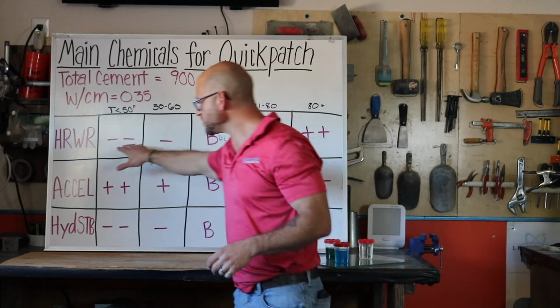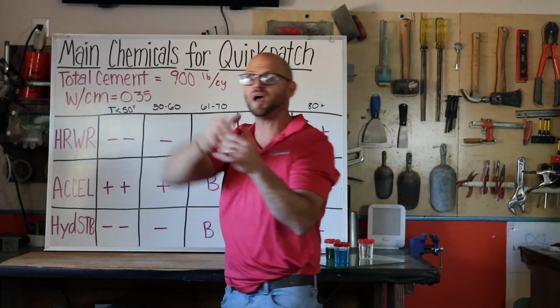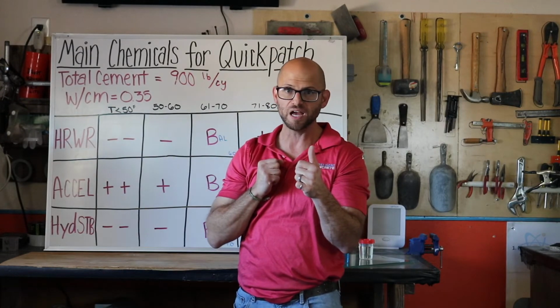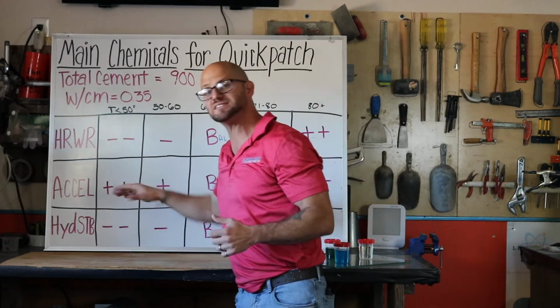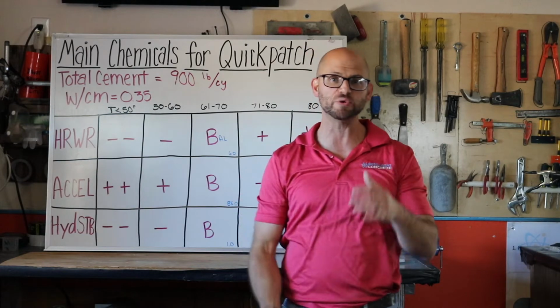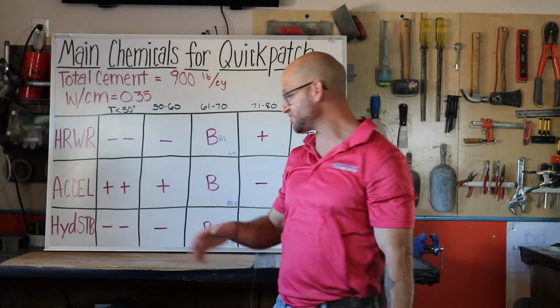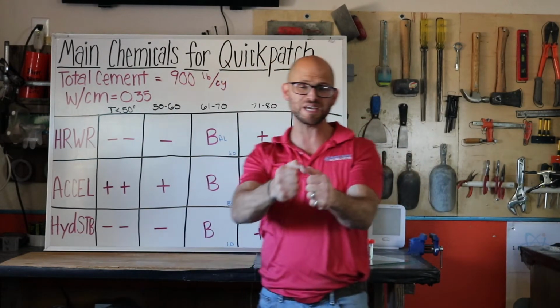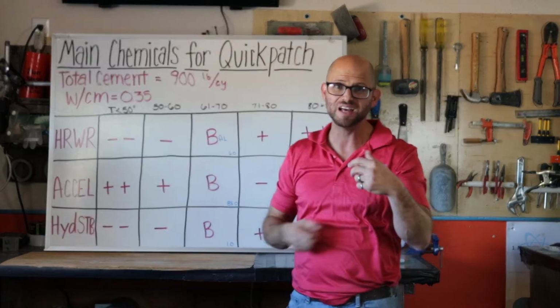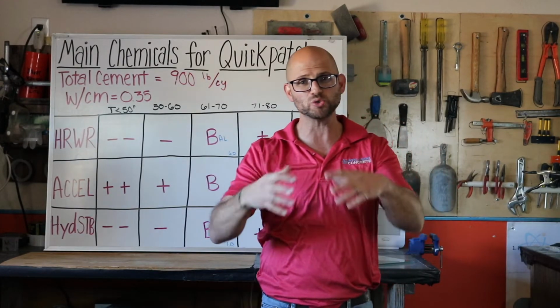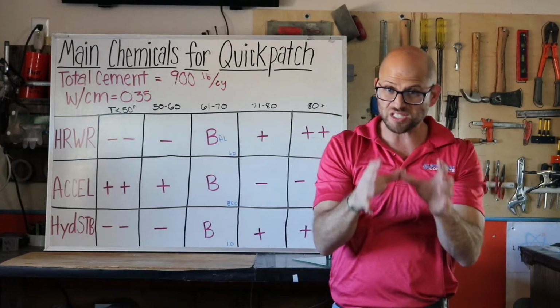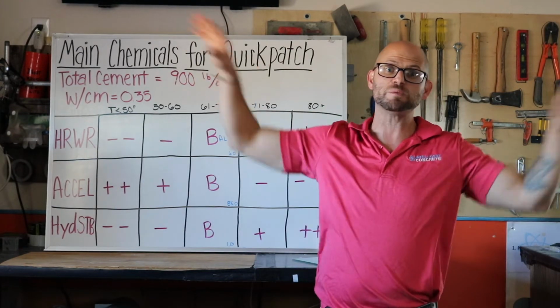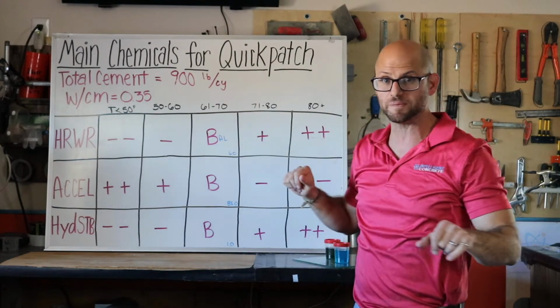Now, if I go 10 degrees colder than that, again, I might go half a step back on my high range water reducer, but I definitely need to bump up my accelerator to get that activation energy. And again, with my hydration stabilizer, I've got to ratchet back on that because I'm already so cold, and most of that energy that I would save for hydration kinetics is now being pushed out to the cold environment.